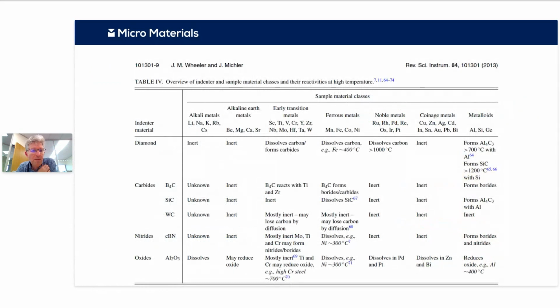So there's a little bit more about this. I recommend this review paper. It's quite a few years old now. It's not absolutely perfect, but it gives a very good guideline into the type of reactivity that you might encounter in the materials choice that you might want to use. And we typically offer different indenter materials, so be it sapphires, be it cubic boron nitrides, tungsten carbides, or diamond, to allow you to test the widest range of different materials at these high temperatures.